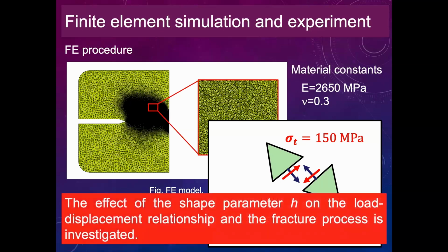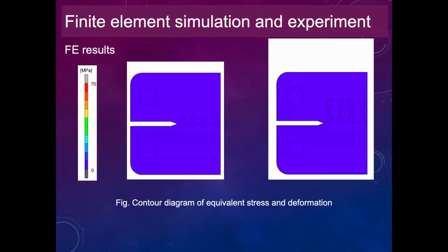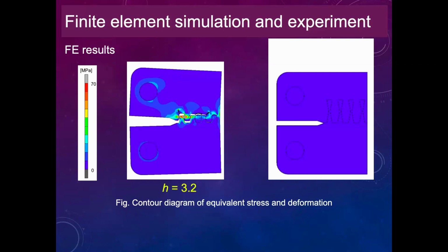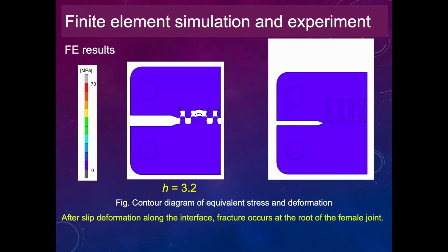The effect of the shape parameter H on the load displacement curve and the fracture process is investigated later. Here we want to show you the FEM result: this is the contour plot of the Mises stress and the deformation of the FEM model under the tensile load. This case corresponds to H equals 3.2. Starting the animation. From this animation, after the slip deformation around the interface of the Sickle joint, the fracture occurs at the root of the female joint.